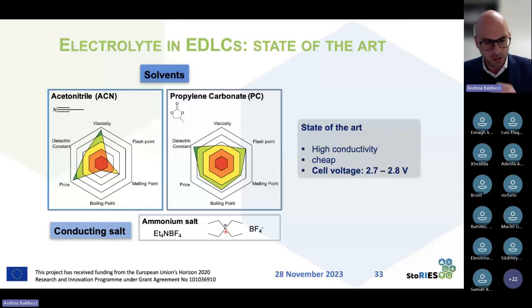And then we take this salt and we dissolve it, as I said before, in typically 1 mole concentration in a solvent. What you're seeing here is a comparison of the properties of acetonitrile, which is the most used solvent in the state of the art, and propylene carbonate, that has been used in some devices in the past, but is now not so used anymore like it was, for example, 10 years ago. And if we look at acetonitrile, we see that it has a good number of advantages. For example, the viscosity is quite low, the price is very good, the melting point is not bad.